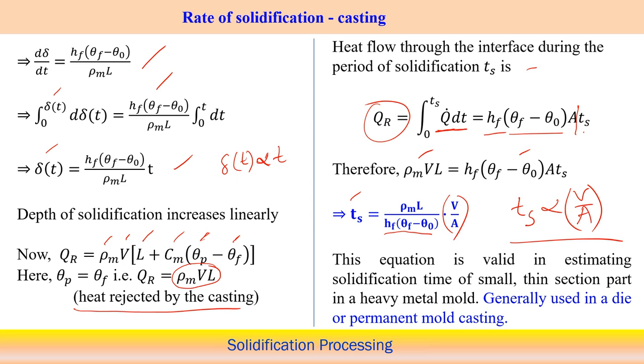In the case of a heavy metal mold, heat is dissipated very quickly through the metallic surfaces, and I am talking about the mold surfaces, through the mold wall. That is why in a heavy metal mold this kind of thermal condition prevails, and based on that we can see that in die casting or permanent mold casting, the solidification time depends on the volume by area ratio.